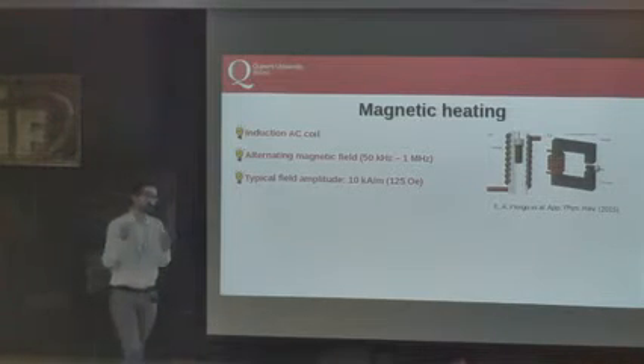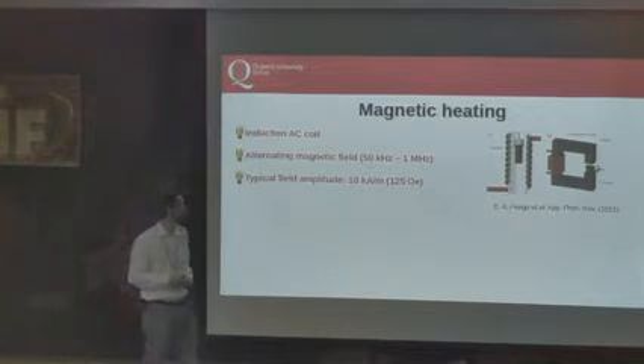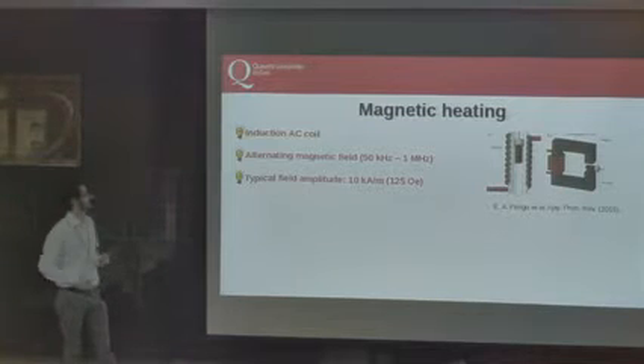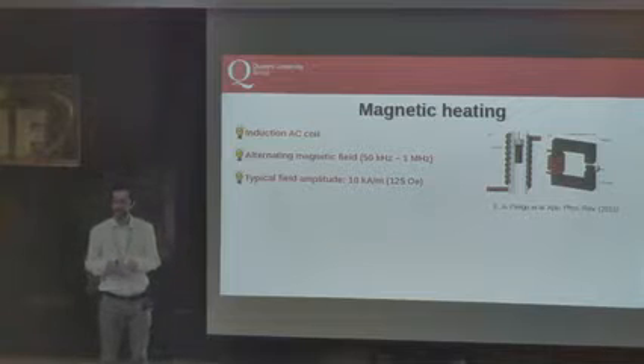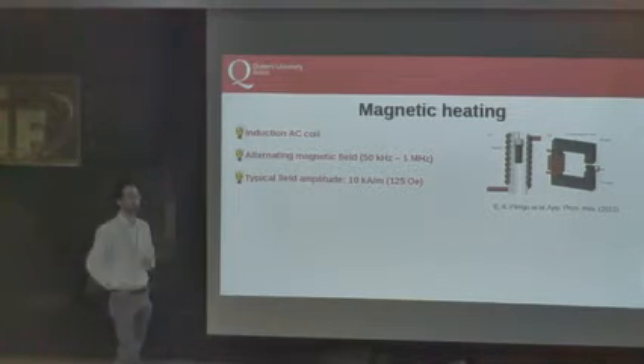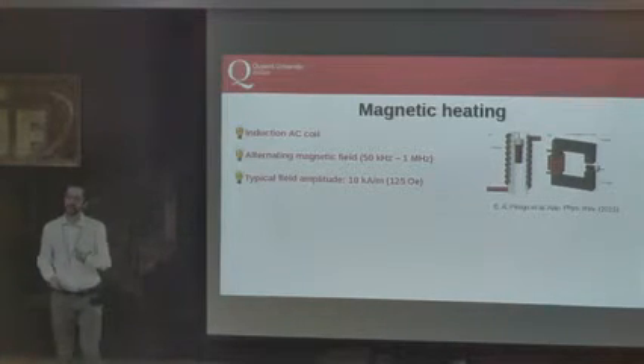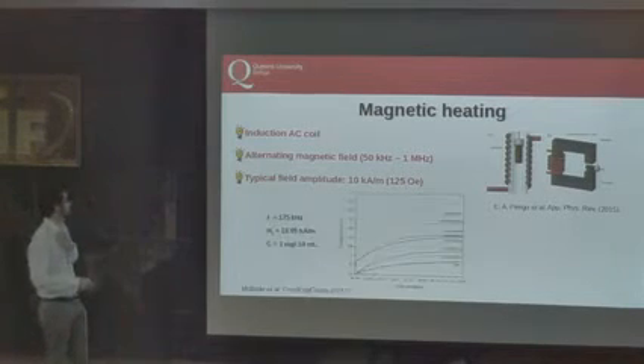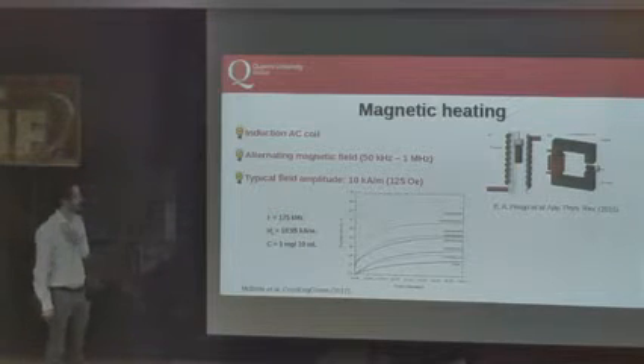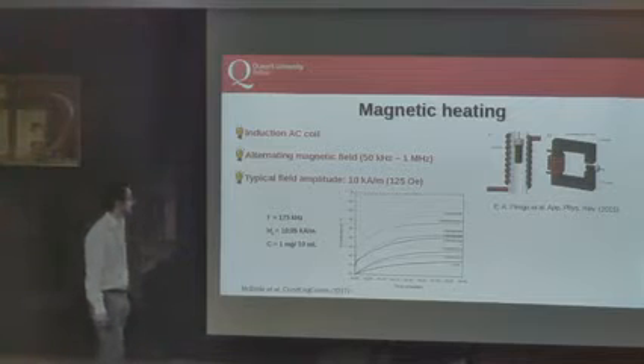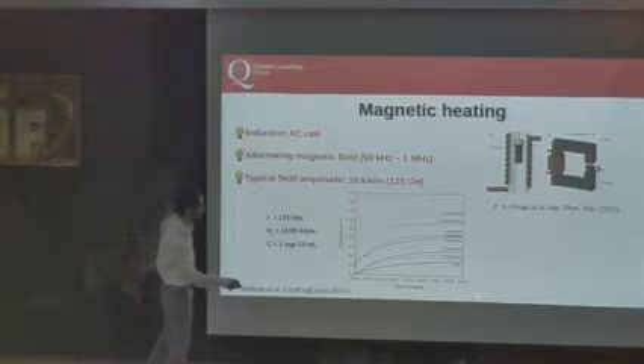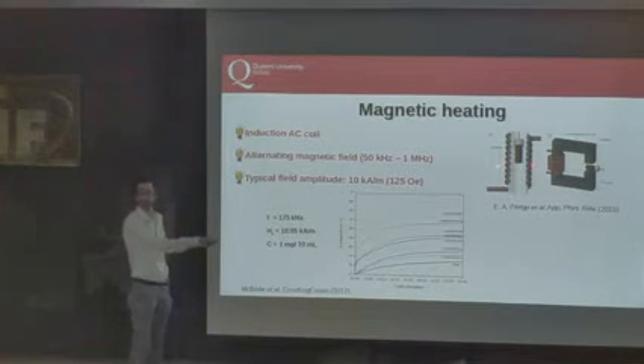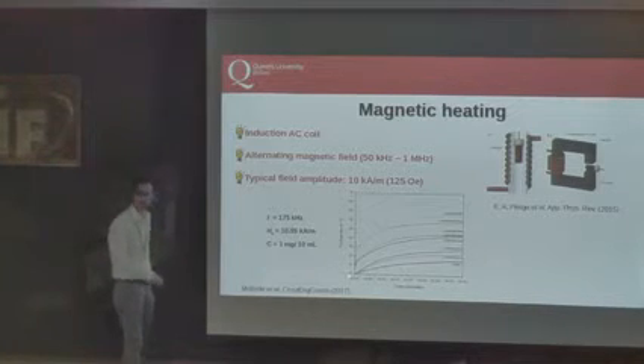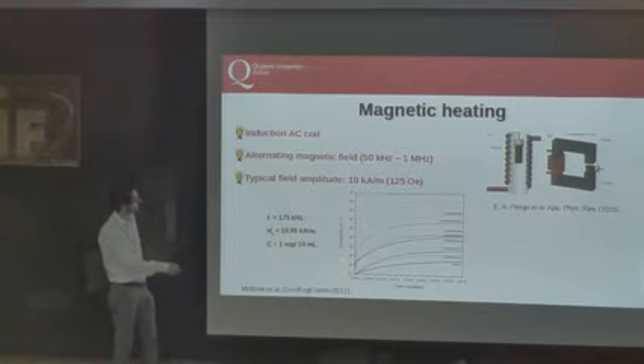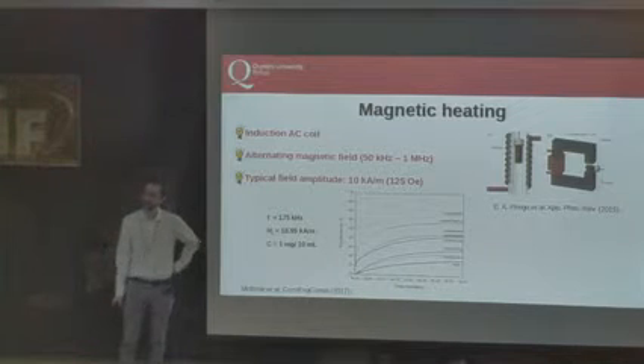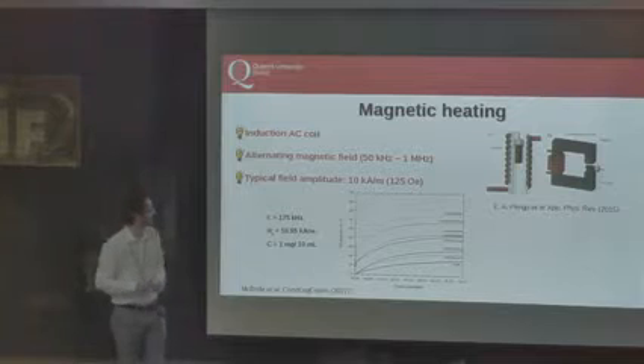And usually we don't want too large an amplitude of this external magnetic field. There are several values, just to fix the attention again, say 10 kiloampere per meter in SI units, in CGS EMU units this is 125 Oersted. This is what they do, not personally what I do. Well, those are the parameters for the experiments that have been performed at the School of Chemistry and Chemical Engineering in Belfast. Here you have a timeline, I think up to 40 minutes, yes, of exposure to the alternating magnetic fields. And this is the temperature. There are many curves, just focus on the temperature. We start from room temperature, and here it goes as high as 60 degrees. There is a little thermometer in the vial. I'm kind of simplifying the experimental setup.